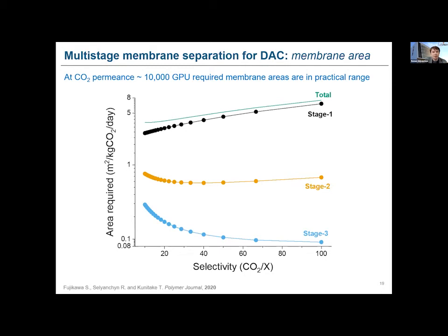As you can see, with the permeances which were used for calculation, which are not our highest, but our reliable permeances at which we can work. So you need just 5 to 6 to 7 square meters of total membrane area in order to operate the system. So these are all process simulation results which we have to prove experimentally.